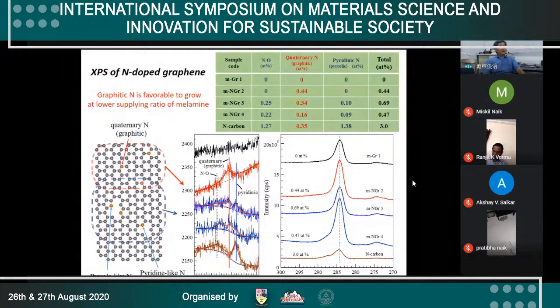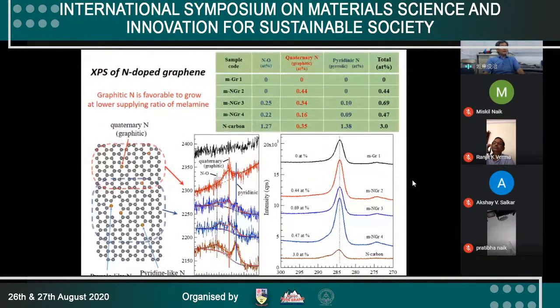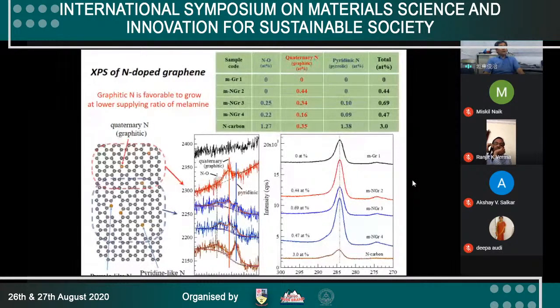Okay, this is a result of the XPS. The center part is the XPS spectrum of the nitrogen 1s level. From the chemical shift, we can know what kind of site the nitrogen is doped in. First, when the melamine ratio is lower, the red line, graphitic doping of nitrogen occurs in the graphene. And when we increase the supplying ratio of melamine, the nitrogen source, pyridine-like doping occurs.